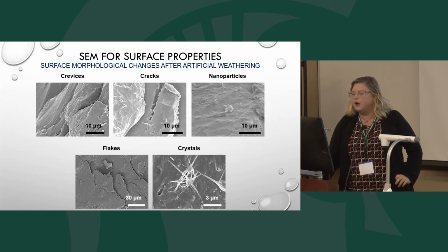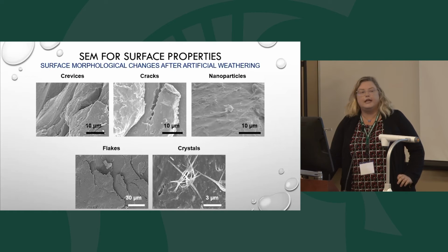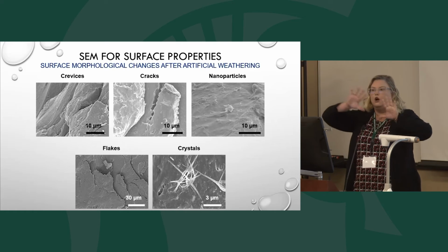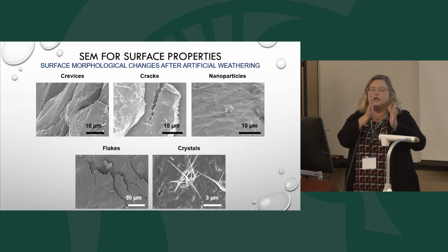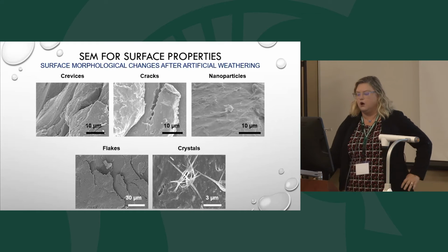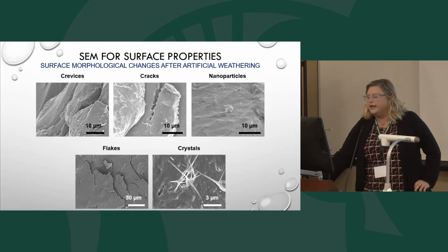This is indeed the same composition. This little dot right here is the same composition as what the microplastic surface is behind it. We see a lot of flaking that occurs. So these flakes will flake off and they may be large in one dimension, but you turn it on the side and their thickness is very, very small. So they're like platelets there.